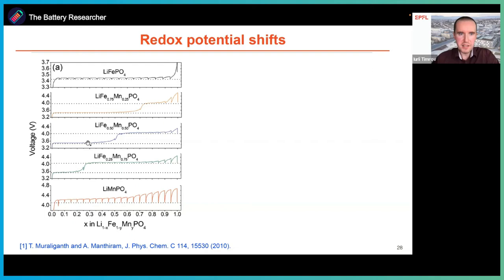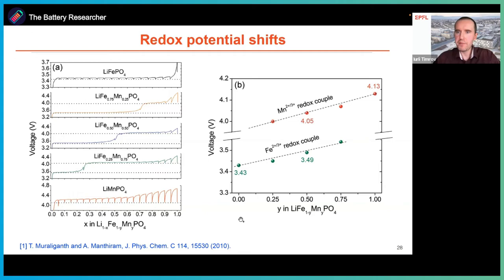But I would like to underline that the voltages do not match exactly with the pristine elements. And this can be shown from the figure on the right. What we see here in red is the manganese 2+, 3+ redox couple. And the voltage is not exactly the same. So we have 4.13 volt in the manganese olivine. However, when we replace half of manganese by iron, the voltage drops to 4.05. And if we do the same for iron, in the pristine iron olivine, the voltage is 3.43 volt. And when we replace half of iron by manganese, it goes up to 3.49. This is known as redox potential shift.